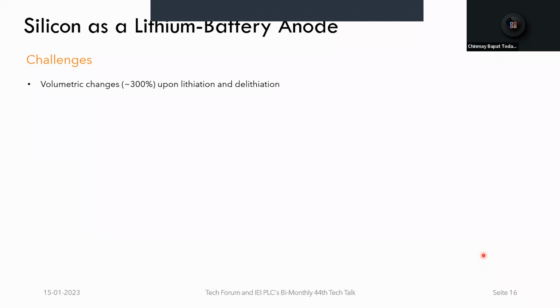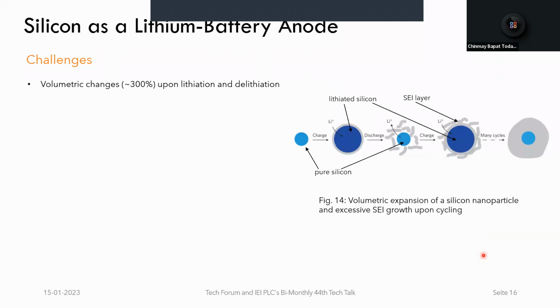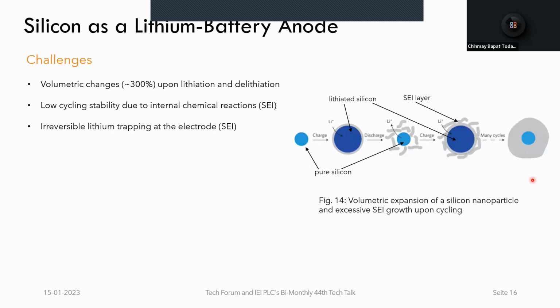But this alloying reaction and the increasing volume is the first challenge for silicon-based anodes. That is its enormous volume change upon lithiation and delithiation. So when these particles continuously expand and contract, they do not retain their structures, as we saw. And therefore, the solid electrolyte interface layer, which I mentioned in my previous slides, gets broken up and reformed, and gradually it becomes thicker and thicker, as we see in this graphic. And as it becomes thicker and thicker, lithium ions, which shuttle between the electrodes, are stuck in the SEI layer or at the electrode. And therefore, we have lower cycling stability due to these internal chemical reactions, and also irreversible lithium trapping at this electrode.